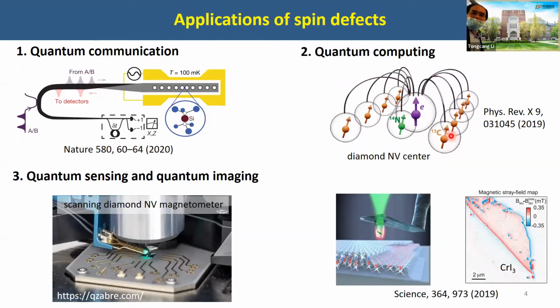This is work done a few years ago, where they realized a 10-qubit system with 1 electron spin and 9 nuclear spins in a diamond NV center. There is a lot of work using diamond NV centers for quantum sensing and quantum imaging. In fact, this is commercially available right now. You can buy a scanning diamond NV magnetometer directly, which can give a resolution of about 50 nanometers and can measure magnetic field very sensitively. Here is an example. You use a diamond NV center to map out the magnetic field distribution of a 2D magnet. So you can distinguish, for example, that a monolayer is a ferromagnet and 2 layers is an antiferromagnet, and you can identify the magnetic property layer by layer.